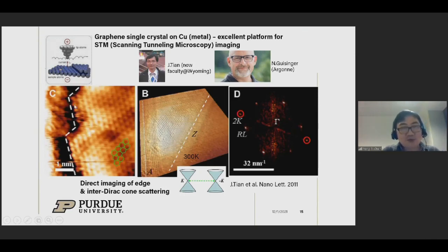First of all, you can take these really striking atomic-resolution images to look at the structure of this graphene edge. In this case, it's mostly along the zigzag direction, but occasionally you can find a different direction, called armchair. Near this edge, you observe a very interesting standing wave pattern, even at room temperature. If you take the Fourier transform of the standing wave pattern, you get discrete spots or wave vectors, which in fact match the distance between two Dirac cones in graphene. I did not mention earlier that in the graphene band structure there are two inequivalent Dirac cones separated by a momentum wave vector, which matches the wavelength of the standing wave. So this turns out to be a direct imaging of the inter-Dirac-cone electronic backscattering that we observe here, even at room temperature. That's a very good use of this type of CVD-grown synthetic graphene on metal.